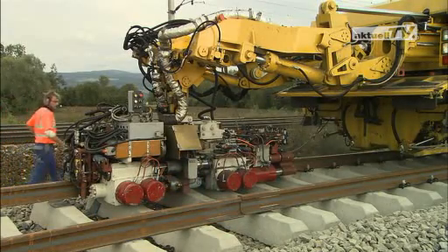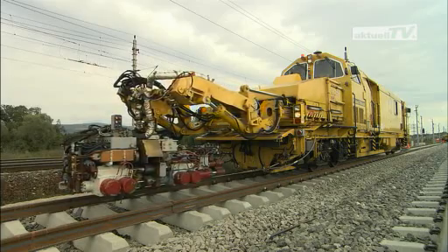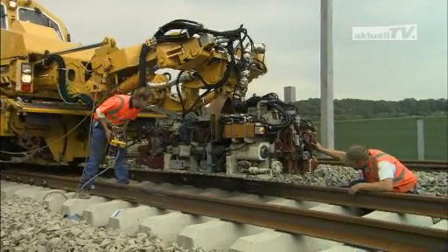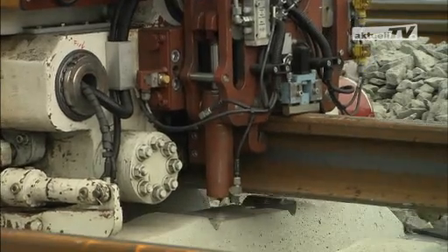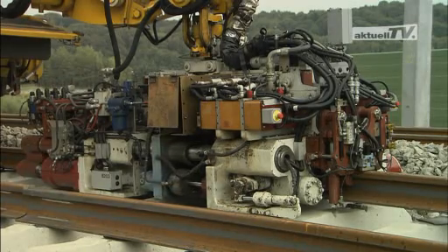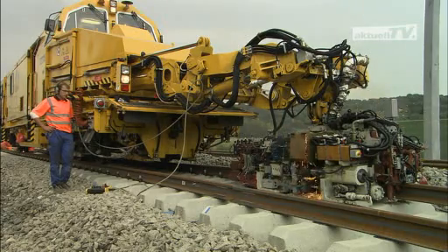Another special feature of this welding robot is that for the first time ever in the world, the power supply is alternating current with a medium frequency of 1000 Hz. This allows the use of small compact transformers in the welding head, and the rectified welding voltage also has a very low residual ripple — a further guarantee for the highest welding quality.